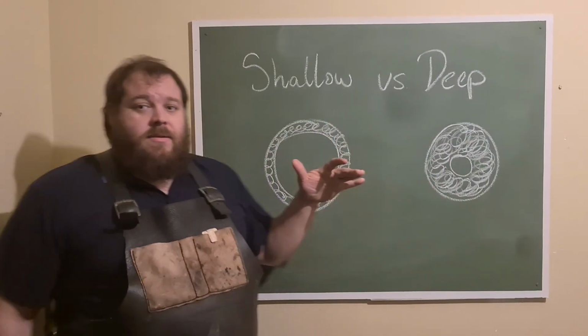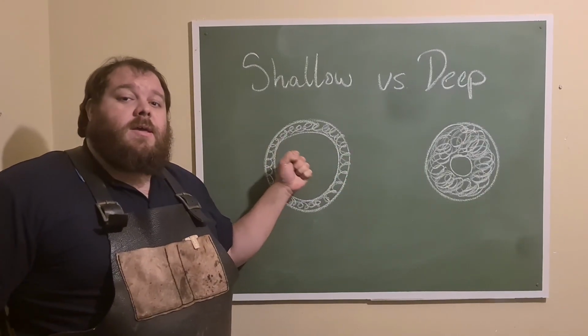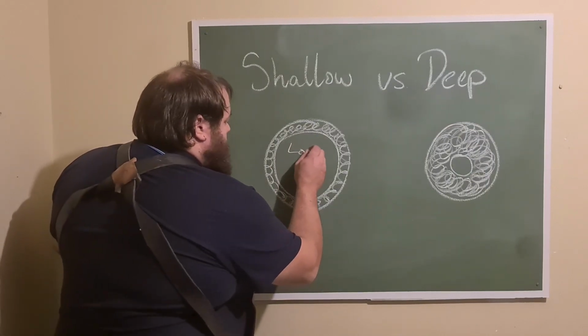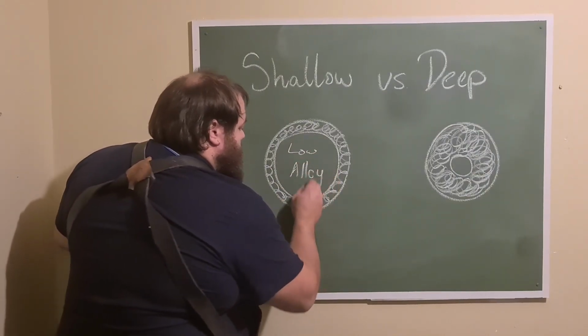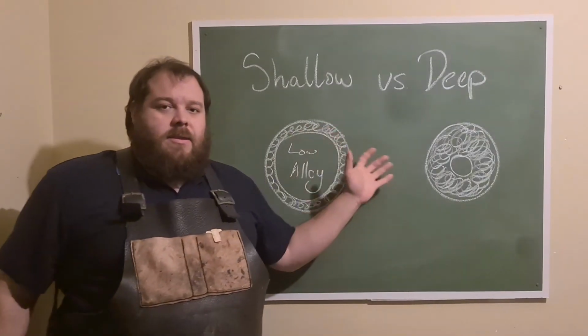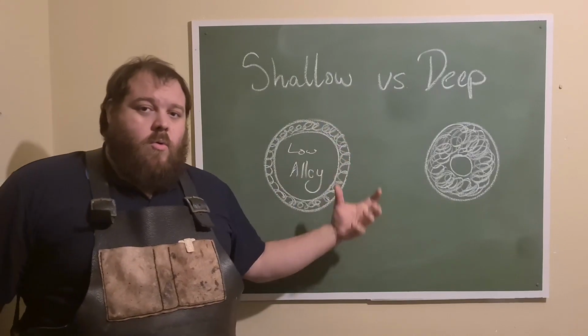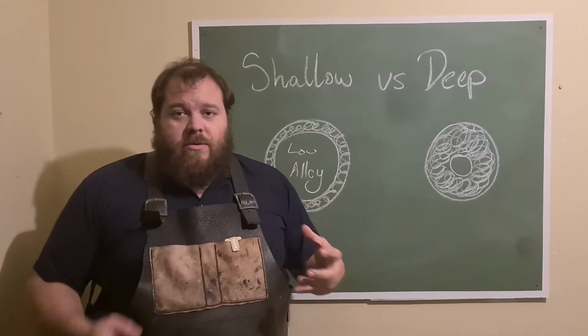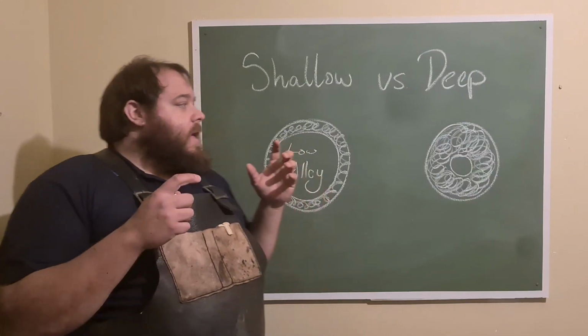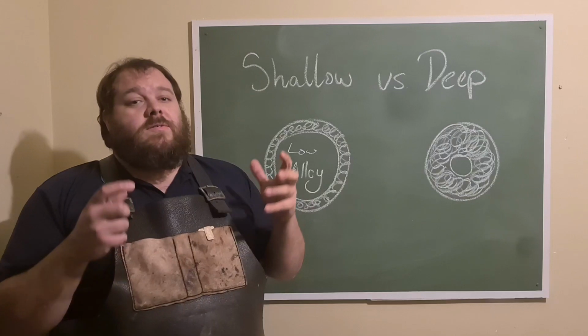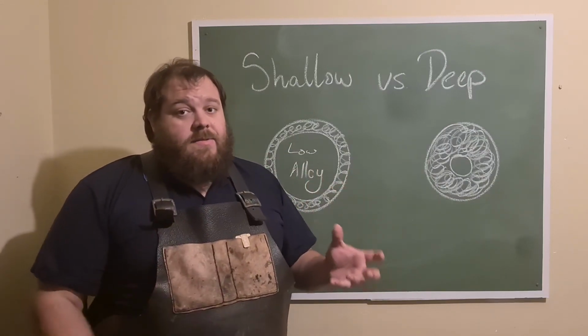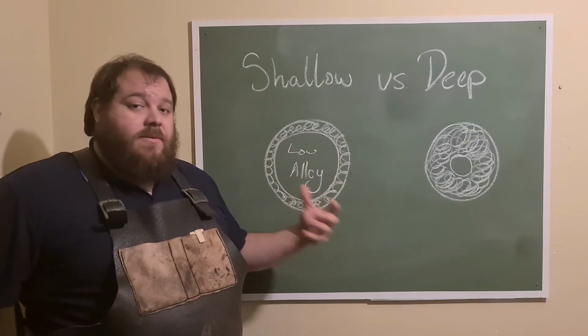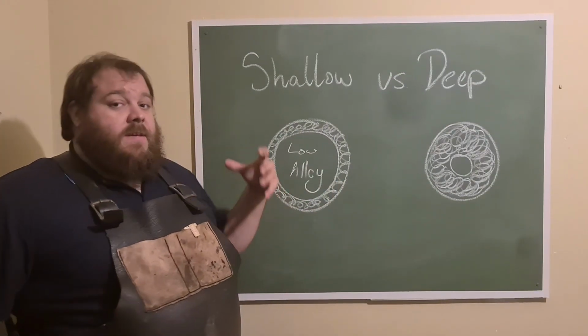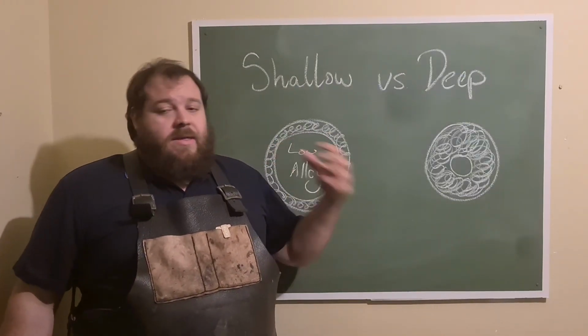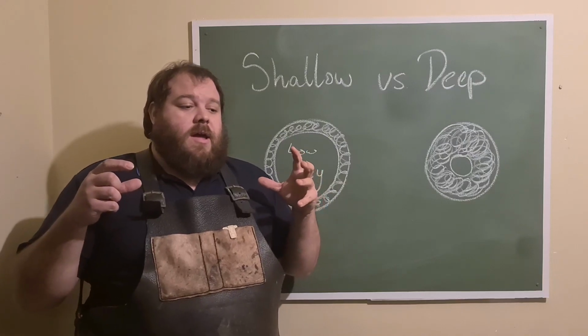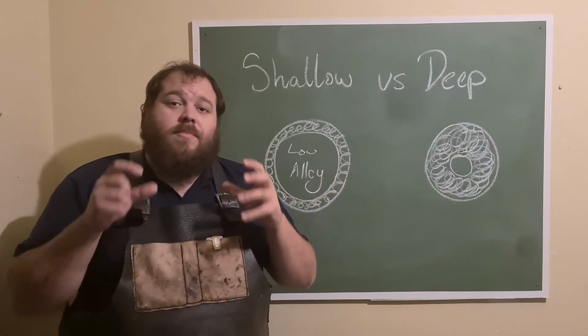The main reason that shallow hardening steels are the way they are is because of low alloy. Alloying contents in the steel will then precipitate more martensite than without it. We all know that steel is a mixture of carbon and iron, but in certain levels, alloying contents such as vanadium and chromium and things like manganese can increase the hardenability or the depth of hardenability of a steel. It does this by attracting carbon molecules. So in the iron, in the steel, there is a natural connection between the iron and the carbon, but that is a very loose connection.